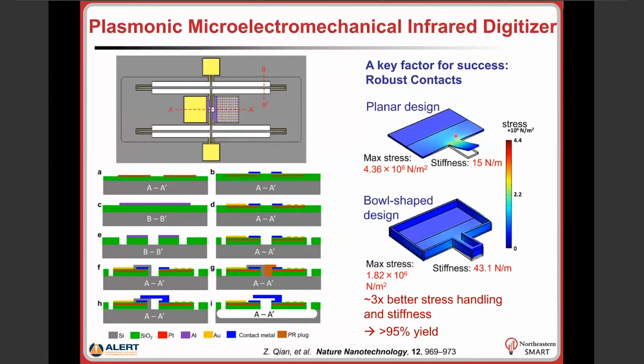In principle, you could use this sort of simple planar design for the metal contact tip. But instead, we came up with this bowl-shaped design, that you can see here, that allowed us to use a very thin film material, metal electrode, that simplifies the microfabrication process. At the same time, using this thin film material allows us to build contact tips that are stiff enough to provide stable and repeatable mechanical contact with the bottom electrode.